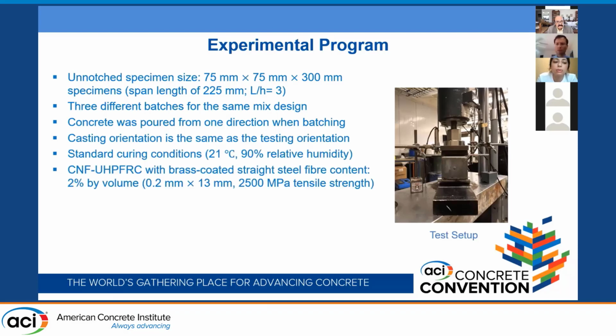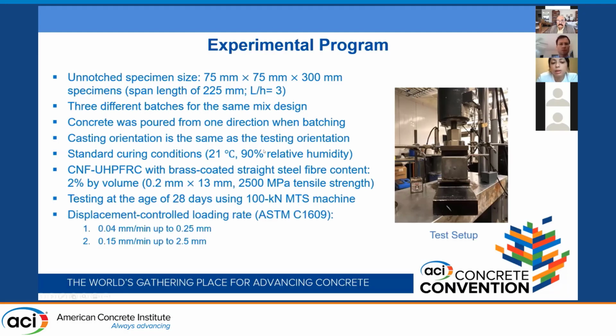As I mentioned previously, we used CNF-UHPFRC with straight steel fiber at a content of 2% and 0.2 by 13 millimeters dimensions. We tested the specimens at the age of 28 days using a 100 kilonewton machine. And the loading rate was divided into 2 stages as per the ASTM C1609. Now, what about the results?